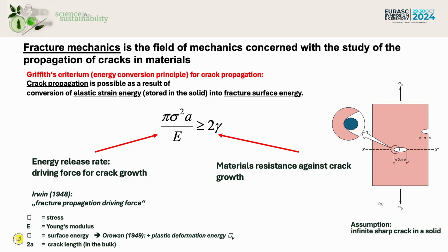By the way, it's an excellent paper, and I always recommend to my students to read this original paper from Griffiths. What is it about? The major message is that defects and faults in materials are responsible for fracture of brittle materials and for failures. That means if we have an ideal solution, then we have a very high fracture strength that we can calculate. In reality, all materials, all systems have defects, have failures.